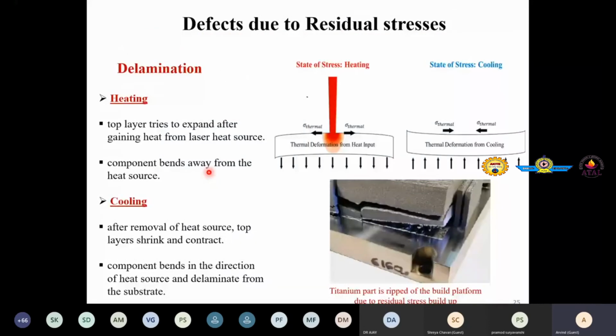So here again it is mentioned that during heating, the top layer tries to expand after gaining heat from the laser heat source. So the component tries to bend away from the heat source like this, right? However, during cooling, after removal of the heat source, when the heat source crosses that location, the top layer shrinks as shown and contracts. The component bends in the direction of the heat source and delaminates from the substrate. This is how it happens. You can see, if stresses are excessive, then this delamination will happen, right?